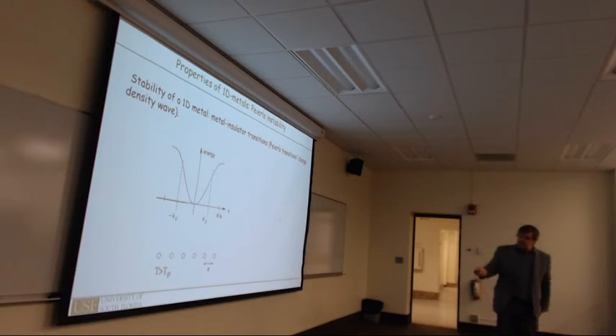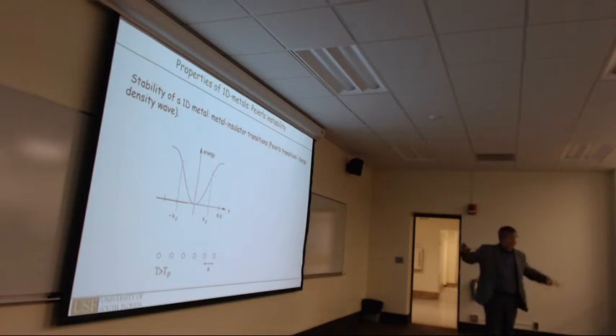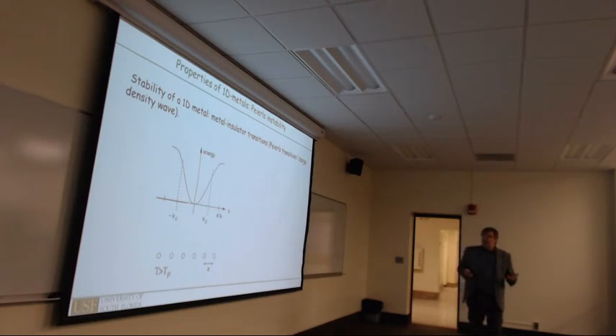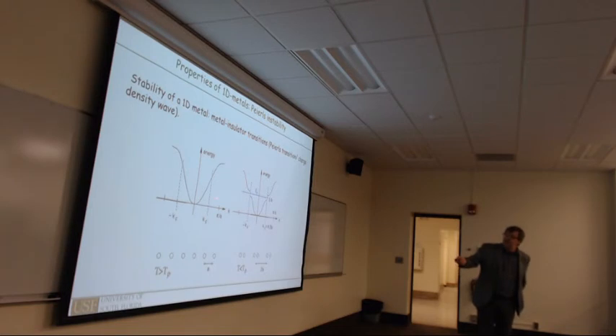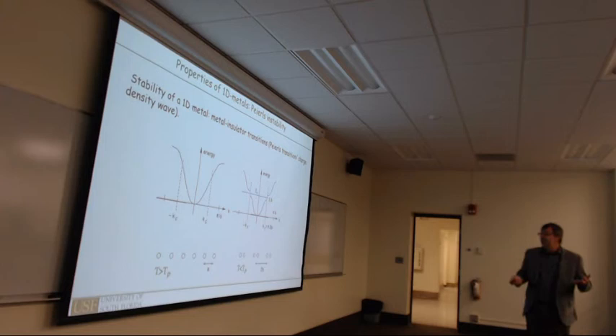Now, if this band is only partially filled, so if your Fermi wave vector is somewhere here, then this downward bending or the lowering of the electron energy at the Brillouin zone boundary does not affect it. But you can lower the energy of the system by moving your Brillouin zone boundary to the Fermi wave vector kF, and then if your new Brillouin zone boundary is here, you lower the energy of the occupied electrons, and therefore lower the energy of the entire electron system.